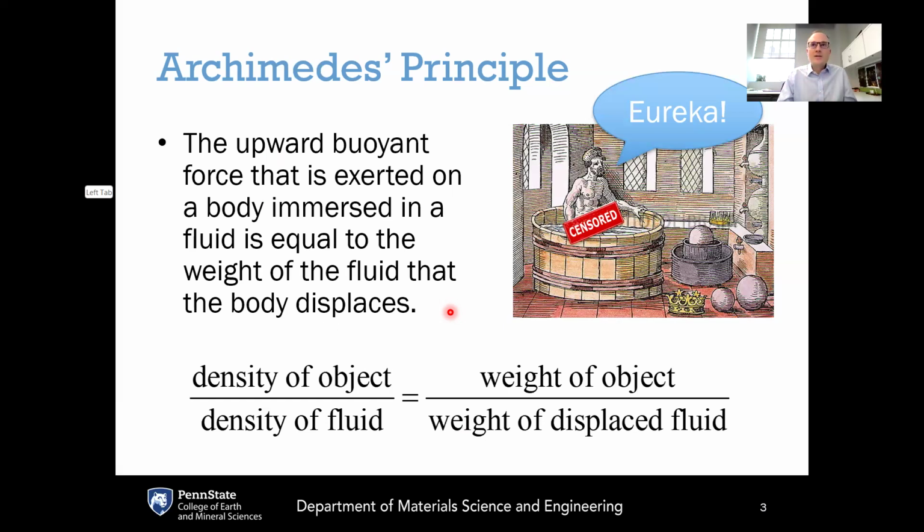The fluid needs to be something that's going to be non-reactive with the material that is under study. In most cases, if you've got a glass that has reasonably good durability in water, you can use water for this and it will work fine. However, there are some glasses that will degrade rather rapidly in water. And so for those systems, you'd want to use some alternative fluid, like maybe an alcohol, for example.